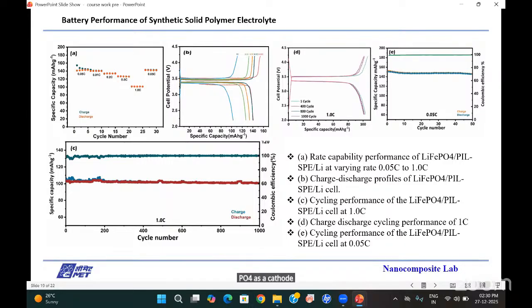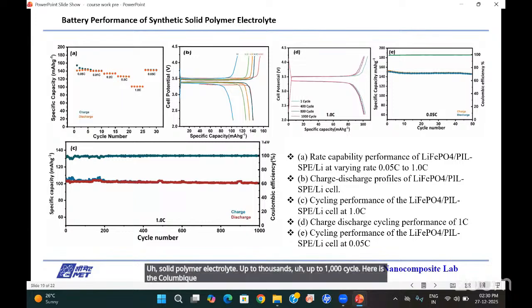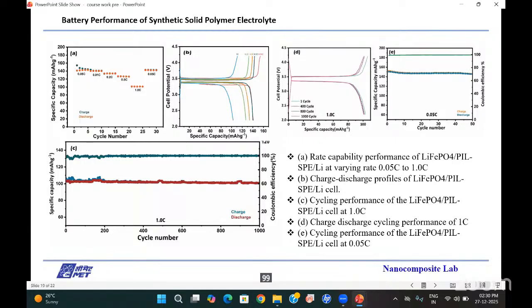Then we are taking the cycling performance of our solid polymer electrolyte up to 1000 cycles. Here the Coulombic efficiency is up to 99.5%, which is the best. Then in figure D, there is the charge-discharge cycling performance at 1C. Hence, these are at the first cycle, 400th cycle, 800th cycle, and 1000th cycle.